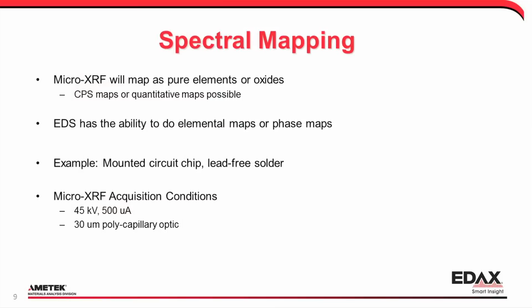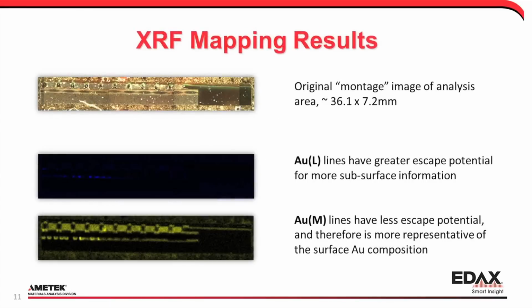And for the Micro-XRF conditions, we have 45 kV in a rhodium tube, 500 microamps, using a 30 micron polycapillary. And so we mapped an area that was roughly 36.1 by 7.2 millimeters. The image you see on the top is the original color image of that analysis area.